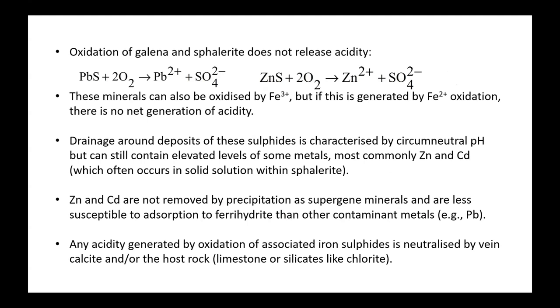Galena and sphalerite, when they oxidize, don't release acidity normally when they're oxidized by oxygen. If they're oxidized by Fe3+, they can generate acidity, but if the Fe3+ has been generated by Fe2+ oxidation, that uses up an H+, so there's no net generation of acidity. So what that means is around mine sites that are characterized by lots of galena and sphalerite, often the drainage is circumneutral, and so it's often called neutral mine drainage.